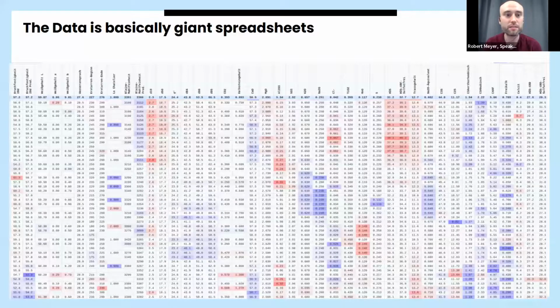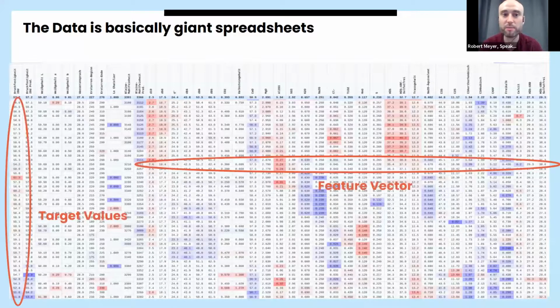Maybe for the ones that are interested, this is how the data actually looks. For every plant that we have, there is basically a giant spreadsheet. Here is the feature vector. Here are some numbers related to the fineness and the particle size distribution. Here are some numbers related to chemical composition. And on the right, you can see some numbers related to the mineralogical composition of the material. One of these rows makes up a feature vector, and on the left you can see the actual results of the 28-day strength experiment where they crushed a cube. This is then our target variable, and with this giant spreadsheet we can train our machine learning models.